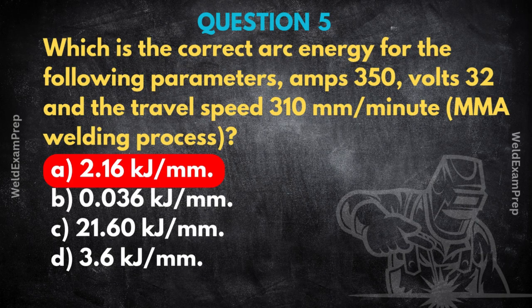And what if they're slightly off? What are the consequences? Even slight deviations outside the qualified range specified in the WPS can be significant. Consistently high heat input might lead to a larger heat-affected zone, potentially failing toughness tests later. Consistently low could mean you're not getting enough penetration, which is a major defect. The consequence could be needing immediate correction, maybe retraining or requalifying the welder, or costly repairs to welds that don't meet the standard. It's all about process control for quality and safety. Process control. That sums it up nicely.